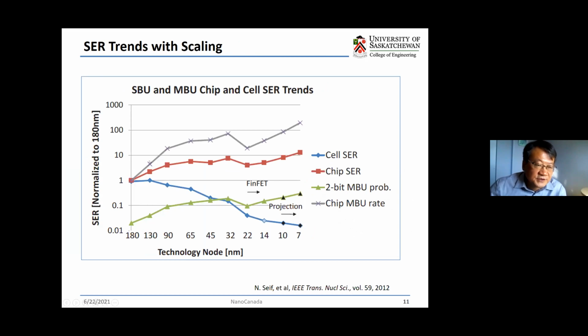Now let's look at one picture. Basically, it's a trend of the soft error rate with scaling. We can see that this technology is scaling from 180 nanometer to 7 nanometer, and the y-axis is soft error rate. We can see that the soft error rate for a single cell is getting smaller. The reason is very simple, because at 7 nanometer the cell size is much smaller than at 180, right? And so the single cell rate is getting smaller.